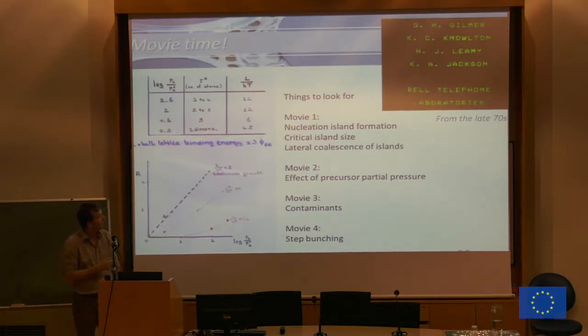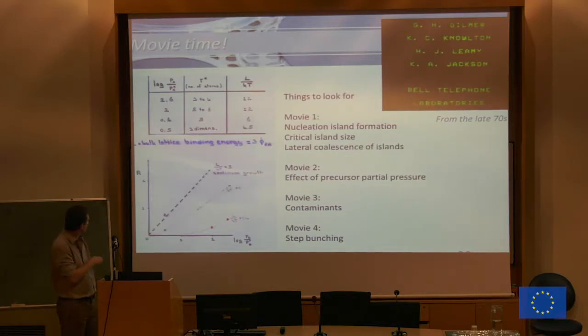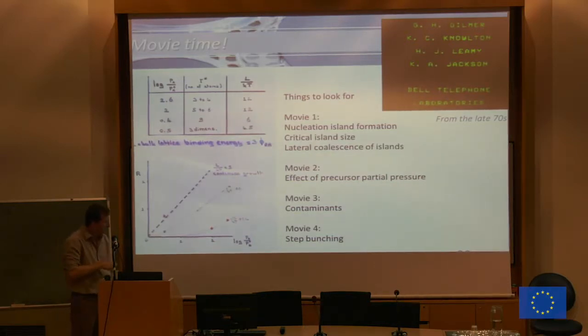So these are movies from these people here at Bell Labs in the late 70s. I apologize for the quality of the movies. They are a little bit dated. But still, I think they illustrate what I tried to say before quite well. So what we will do is show the growth rate as a function of the logarithm of the pressure over the reference pressure. Remember the expression for the chemical potential, it's this that you are changing. So you change the overpressure. And we will work for the first two movies at 2 different points, so 2 different values of this oversaturation.